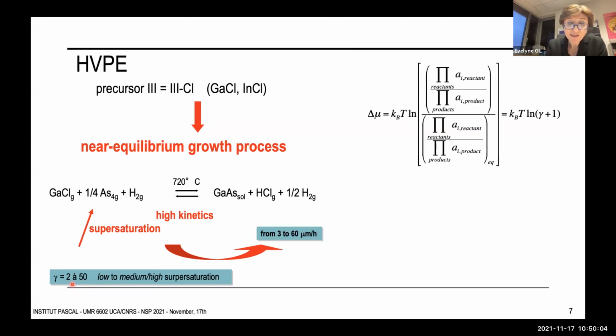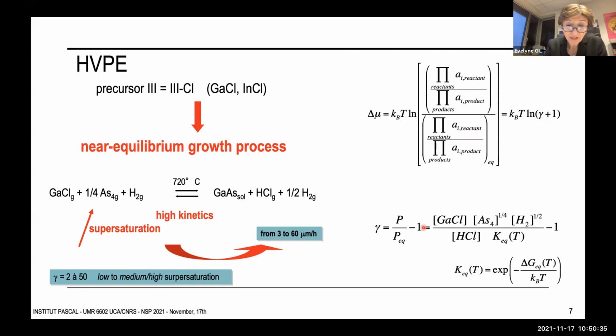So if you look at the values of the supersaturation in HVPE, it seems that HVPE also operates at moderate or low supersaturation. So HVPE is not necessarily a high supersaturation process. And indeed, we must not forget that we supersaturate with respect to a reference, which is equilibrium of the reaction, obviously. And if you want to grow, so shift the reaction towards the formation of solid, we have to supersaturate the vapor phase, which is expressed by the excess of the chemical potential that can be linked to an experimental supersaturation parameter, which is easy to calculate here from the partial pressures of the species that are introduced into the reactor and the equilibrium constant, which can be calculated from the Gibbs free energy of the reaction at equilibrium.